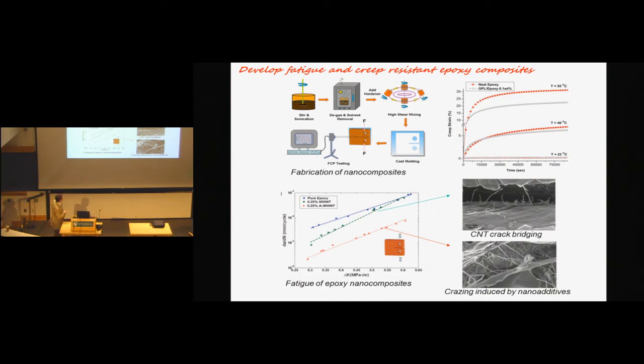Another example is how these materials behave under fatigue conditions. Now, we did two types of tests, two types of materials actually that have been developed. One in which we mix epoxy with carbon nanotubes, pristine carbon nanotubes, and another one in which we mix epoxy with carbon nanotubes functionalized with amine. Now, amine is the cross-linker in epoxy. Okay? So epoxy, as I said before, is a molecular network in which the chains are actually bonded together, cross-linked with small groups from this molecular class, right, with amine groups. And we functionalize the carbon nanotubes with that cross-linker. So they presumably stick better to the matrix.